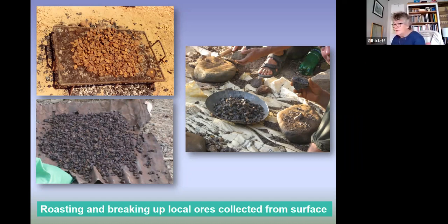hilltops. We roasted it. That means we just heated it in an open fire to further oxidize it and to drive off water vapor. And the two images on the left show it during roasting, and then after roasting, and you can see it's changed color quite dramatically.